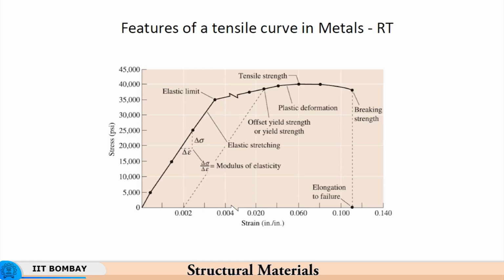So, if you draw a line parallel to this Hooke's law region, parallel to the Young's modulus line, the elastic modulus line here, then you will have at 0.2% strain, 0.002 strain. Okay. So, wherever this line intersects the curve, you draw a line parallel to this Young's modulus line, and wherever it intersects the curve, that is your yield point. So, what is this?